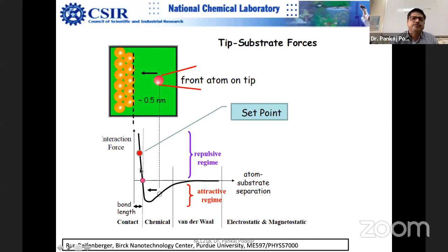When you do atomic force microscopy and set the set point, basically you are setting this distance, how high you are hovering from the surface, that is, how strongly you're pressing against the surface, and that decides your topography. You don't want to press too hard or too soft. This point is extremely important. This is the chemical force range, quite close to the surface, and then comes our van der Waals force, which dies out after around 5 nanometers, maximum 10 nanometers. You won't get van der Waals forces beyond that, and beyond that you have electrostatic and magnetostatic forces.